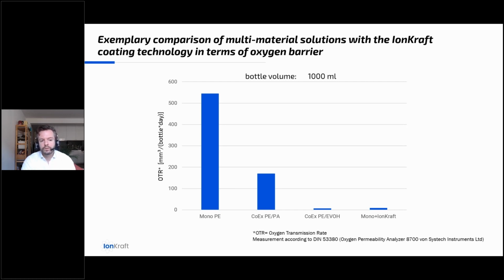And then you have the co-extrusion polyethylene and EVOH combination. And EVOH is a very strong barrier plastic in terms of oxygen barrier. And you can see that the OTR is actually reduced dramatically by it. And what you can also see is that our coating system applied on a monomaterial can reach the same, or almost the same OTR barrier as the coex. So we are well competitive even with the EVOH barrier plastic, and we are much better than coex structures containing polyamide.